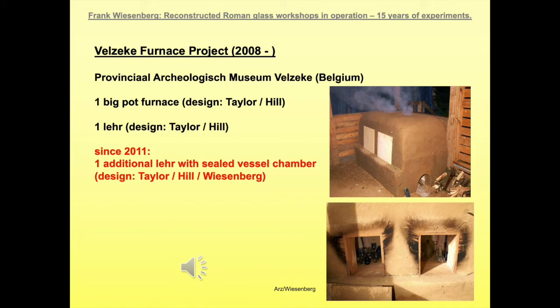Since the small lehr at Wiesenberg produced a kind of dulling effect on the surface of a couple of glass vessels, it was decided to create a different kind of lehr with a sealed vessel chamber to prevent the hot exhaust gases from attacking the surface of the freshly blown glass vessels. This large annealing oven was built in 2011 and featured a sealed closed vessel chamber. It works, it's hard to operate, but the vessels are very clear and shiny, so they feature the correct condition of their surface.